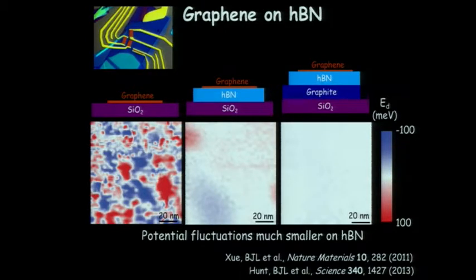spatial extent is also spread out of the charge fluctuations. And that's because all you're doing is you're basically displacing the charge traps that are here at the silicon oxide substrate, displacing them away from the graphene. So they become weaker in intensity, but since they're further away, they have a larger spatial extent. If you instead use a graphite gate here underneath, so graphite being a metal or a semi-metal, can screen all of the charges which are sitting in this silicon oxide.